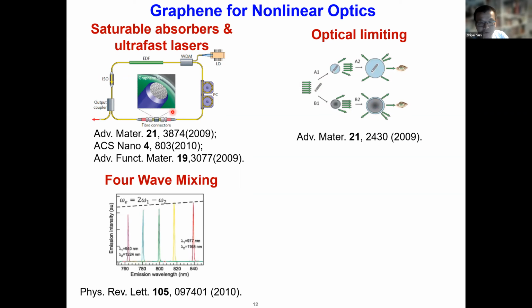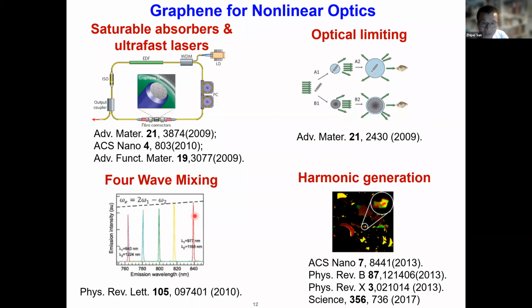Four-wave mixing has also been demonstrated with graphene. Nowadays, people can even use four-wave mixing in graphene for very high-speed optical switching up to 10 gigabit per second. Third harmonic generation has also been demonstrated a few years ago, including results from my university, and high harmonic generation has also been demonstrated a few years ago in graphene.